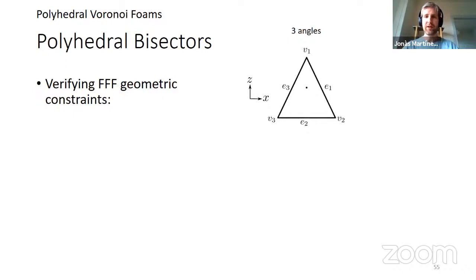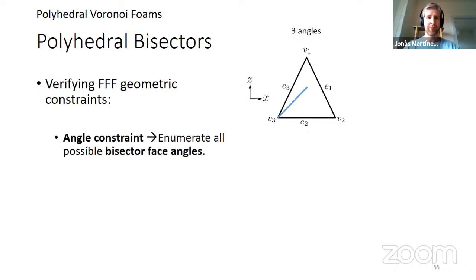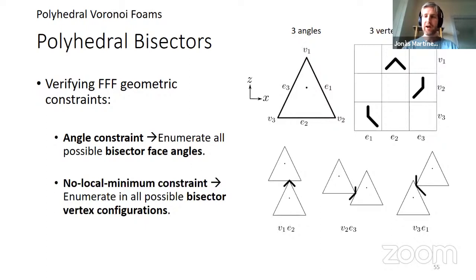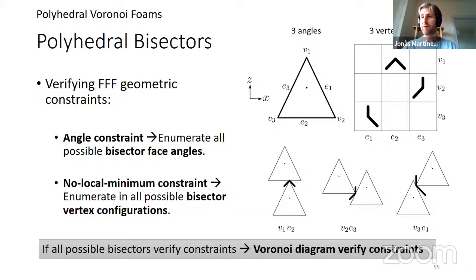So what we do basically is we take a distance. We have a method to enumerate all the different angles that can arise. And we have another method to enumerate all the possible configurations of the bisector. So here, in 2D it is very simple, and in 3D there are more cases. But basically, that's the idea behind this project. And once you have verified that the bisectors are always self-supported, you can also show that the Voronoi diagram is, as a consequence, self-supported and printable.